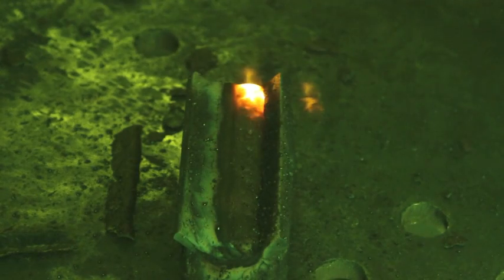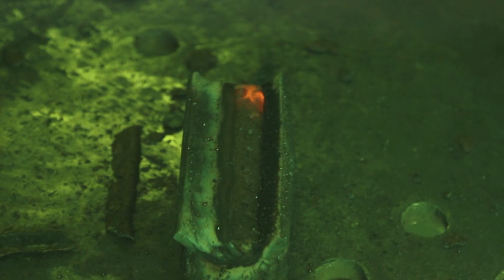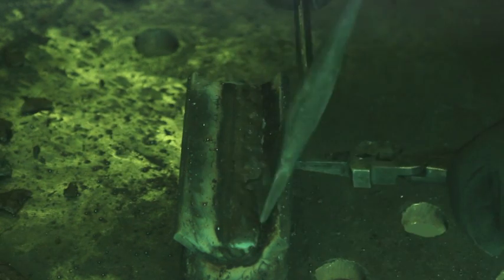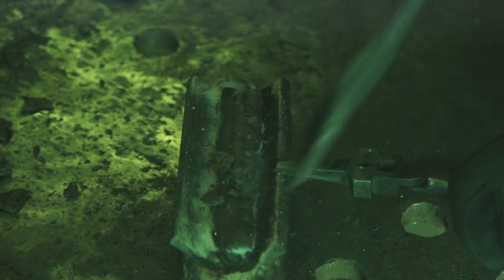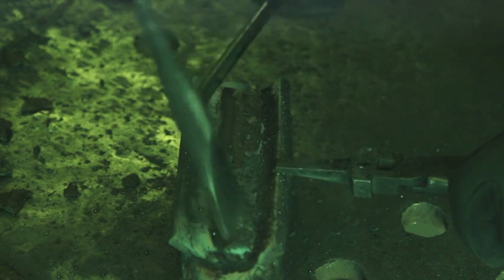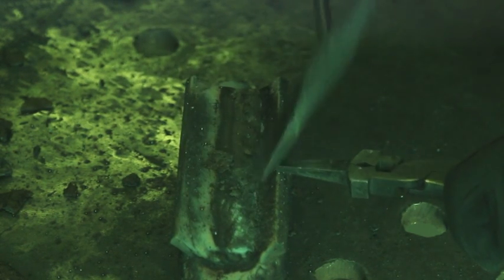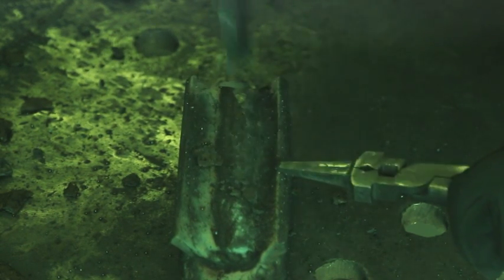But more important than that, and what I really want to show off here, and keep in mind, I didn't change the settings at all. The wire speed and the voltage are the same. The only thing I've done here is, number one, I have made my stick out way too short, and number two, my travel speed, I increased it dramatically.